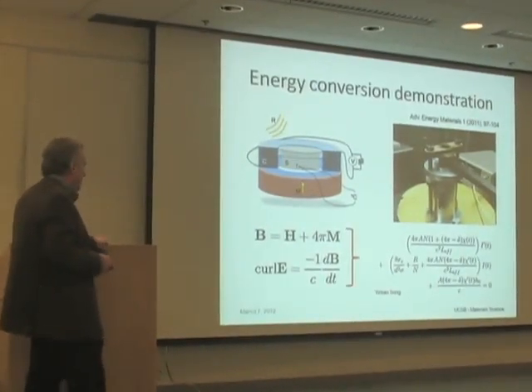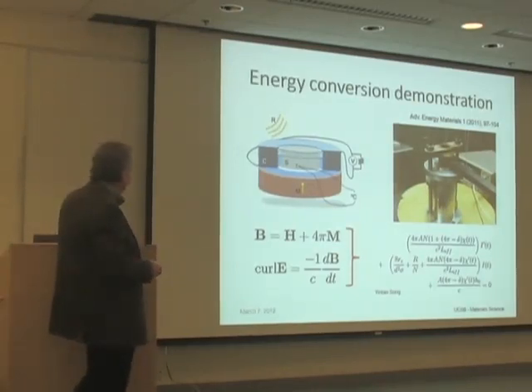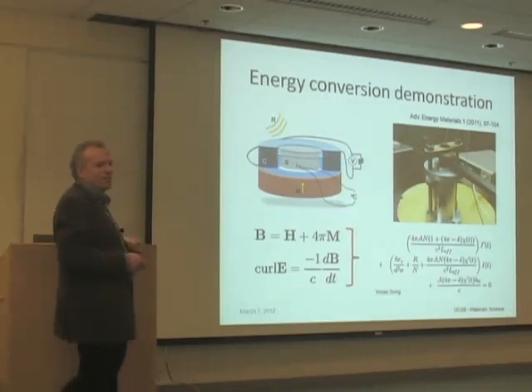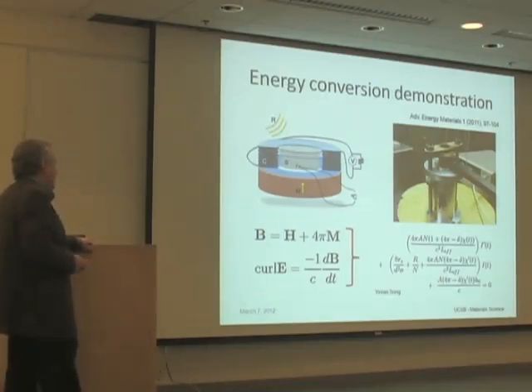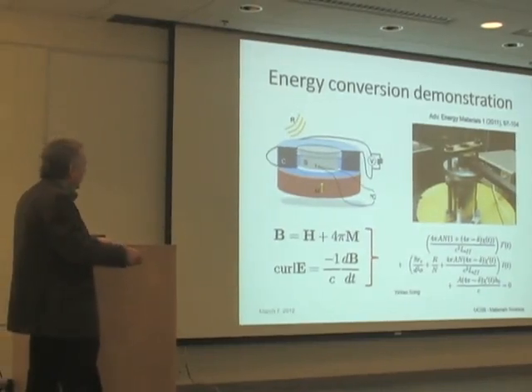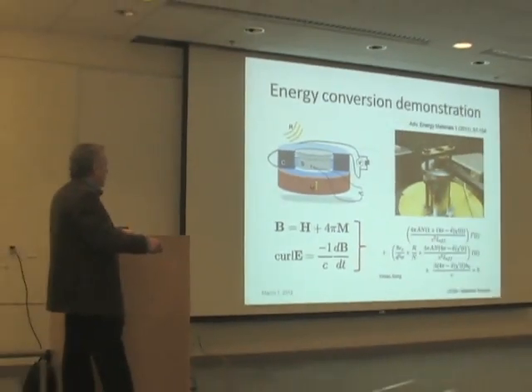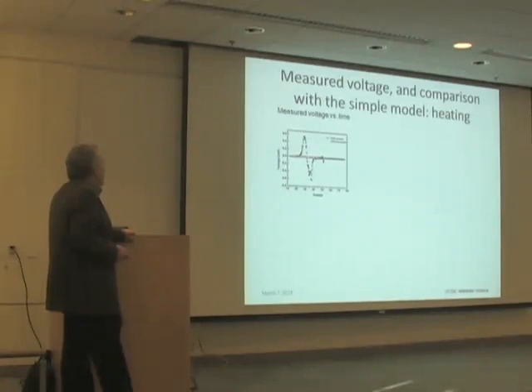So if you make the shape of the specimen correct, and you also think about some of the other micromagnetic aspects, a big dM/dt gets translated into a big dB/dt. And dB/dt is curl E. So in other words, with the changing magnetization, you induce a current in the coil. And there are no moving parts, and of course there are many different ways to design this. This is a little model based on those two equations and cylindrical symmetry, and all the constants are known. And in the experiment we see the voltage pulse, and there's another voltage pulse, because there was a rapidly decreasing magnetization on the other side.